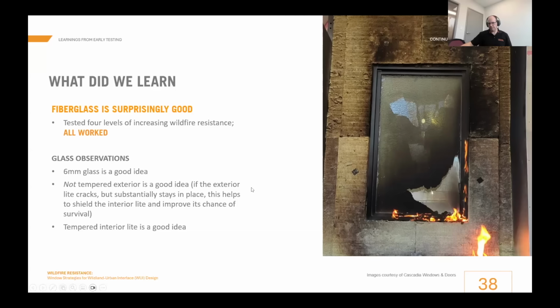By comparison, if the outside glass is annealed, it will crack, and it will crack sooner than if it's tempered, but it tends to stay in place. Like a cracked annealed glass, if it's captured on all 4 sides by window frame, still tends to stay there. So it kind of stays there like a shield hanging in front of the inner pane. And you only really care that the inner pane survives. Now, about the inner pane surviving, temper the inner pane. For sure, that's probably the most significant glass observation. Temper the inner light.